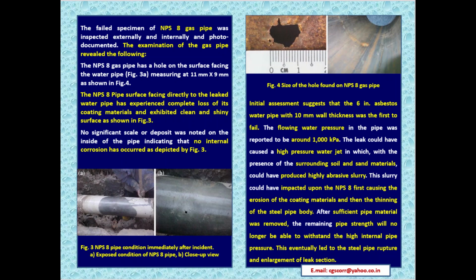The NPS 8 pipe surface facing directly to the leaked water pipe has experienced complete loss of its coating materials and exhibited a clean and shiny surface as shown in figure 3. So figure 3B gives you the close up view. There is a hole and the whole coating on the surface is removed and the surface has a shiny appearance. No significant scale or deposit was noted on the inside of the pipe, indicating that no internal corrosion has occurred, as depicted by figure 3.